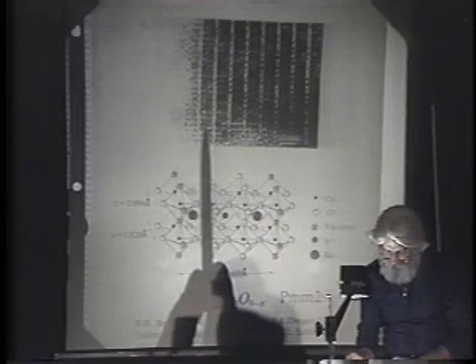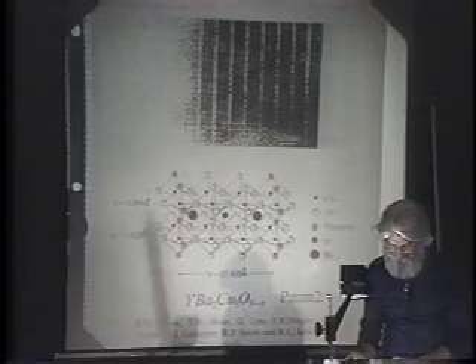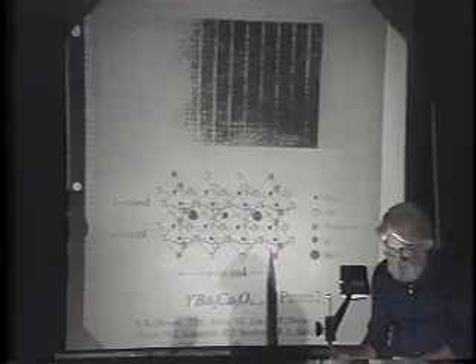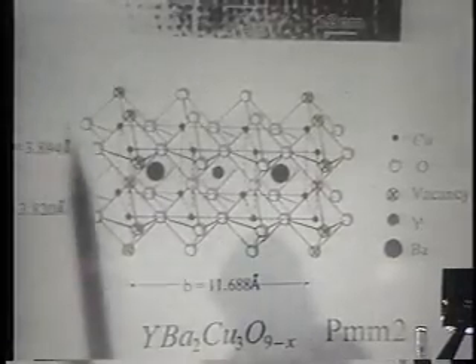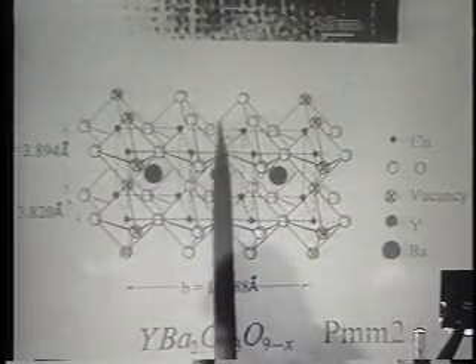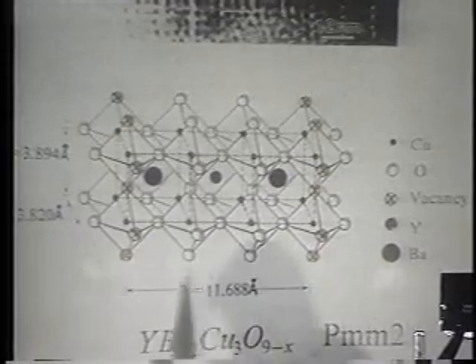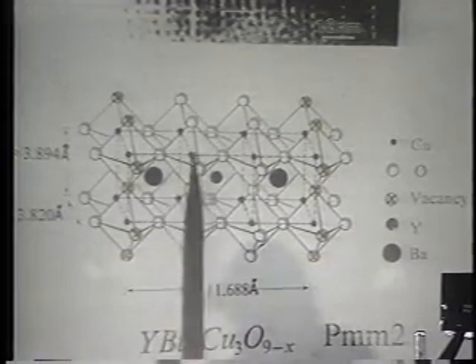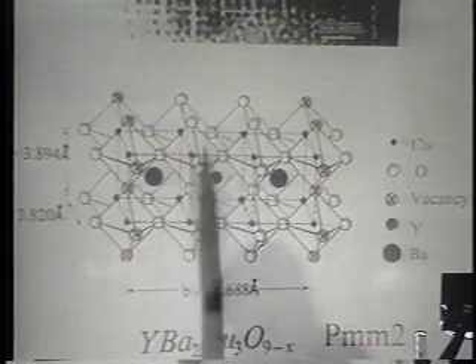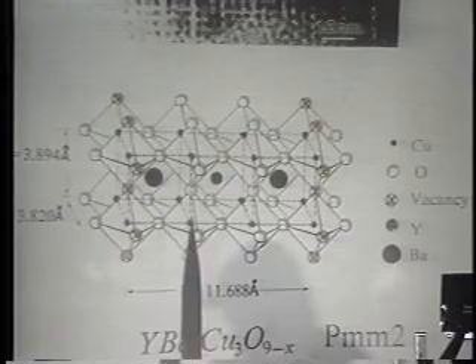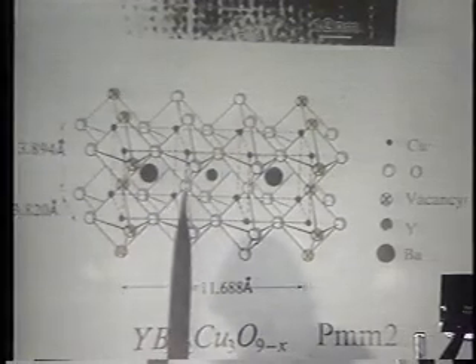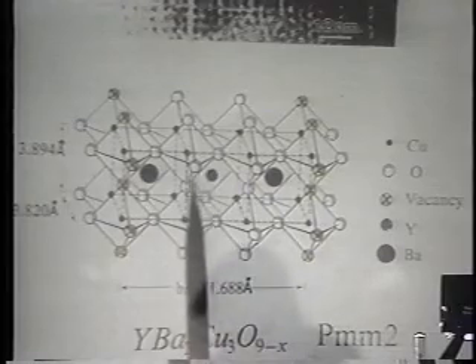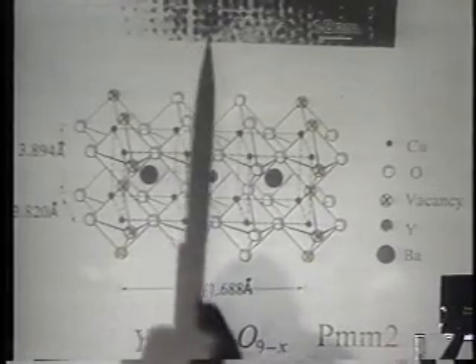The other thing to notice on this micrograph is this large white space in here. And our beginning thoughts were that these were oxygen vacancies in the copper basal plane, and you see here we've marked possible candidates. We really can't say anything about the oxygen vacancies in the yttrium plane. They could or could not be there according to these data. If they are there, I'm still a little concerned about how yttrium 3+ would collect enough negative charge to satisfy its valence. Perhaps it's not yttrium 3+, perhaps it's some other valence, and that should spur on some core level spectroscopy on yttrium.